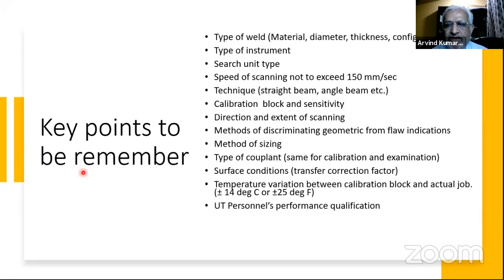The type of couplant. It is important that we use the same couplant for calibration and on the job. If there is a difference in the couplant between calibration and the job, the transmission characteristics would be different and your results will have this error. Also, the couplant should not be detrimental to the surface where you're using UT, particularly for stainless steels. Again, the requirements are the same. The couplant used should not have more than 250 ppm of sulfur, chlorides and fluorides.